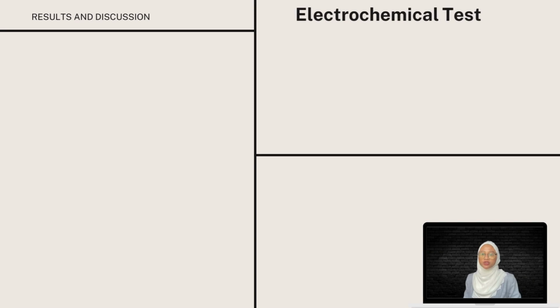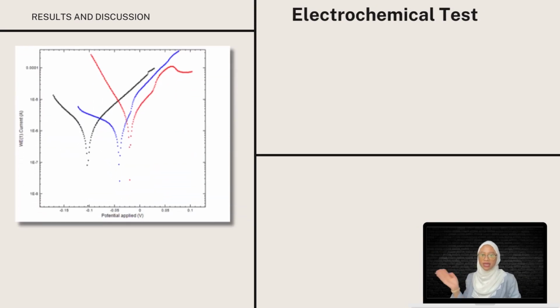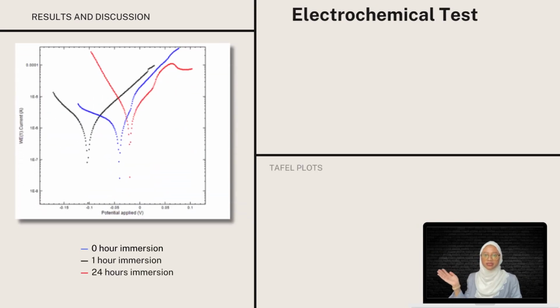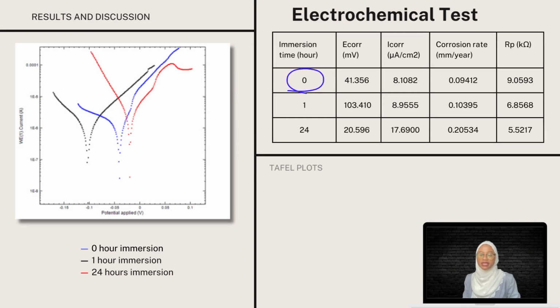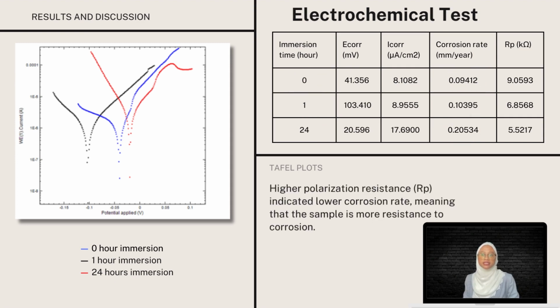As we proceed to the electrochemical test results, the left-hand side shows the table plots of 3 parameters studied in this coursework. From the table, 0 hour of immersion had the best corrosion rate, in which it only corrodes at 0.09412 mm per year, compared to 24 hours of immersion with 0.20534 mm per year. Lower corrosion rate also indicated higher polarization resistance, from which we may deduce that shorter immersion time means that the sample is more resistant to corrosion.